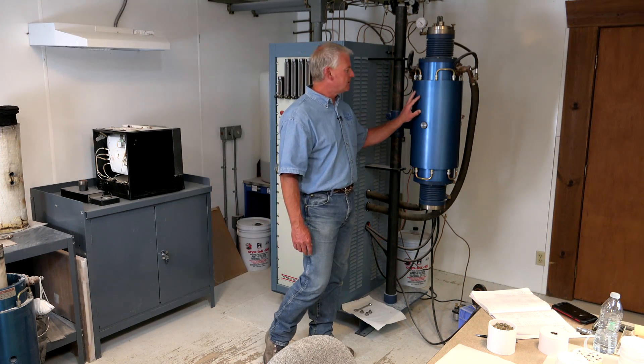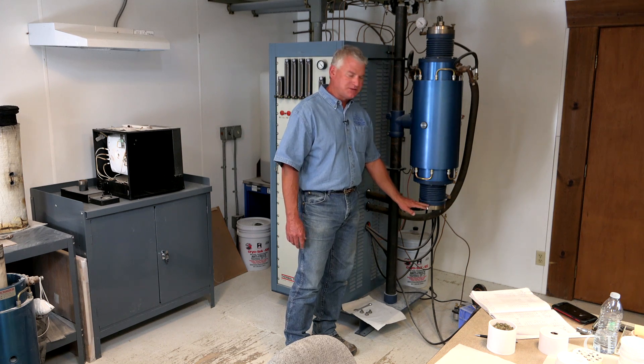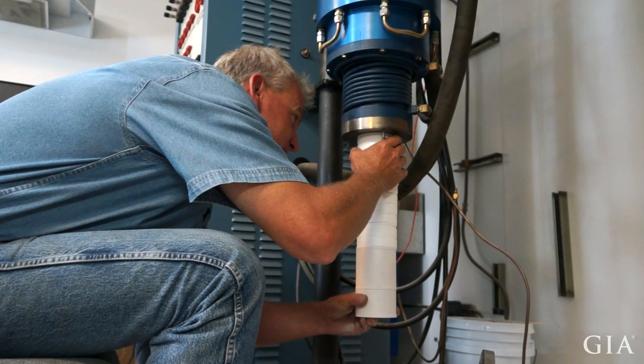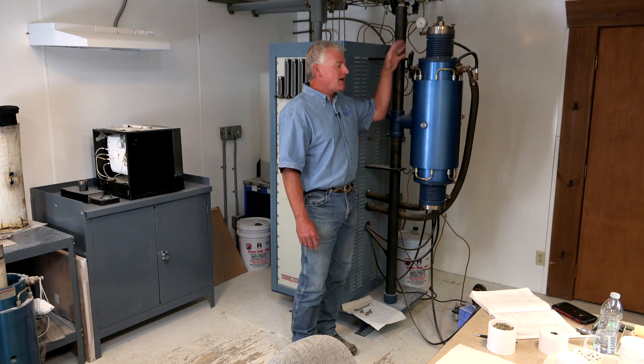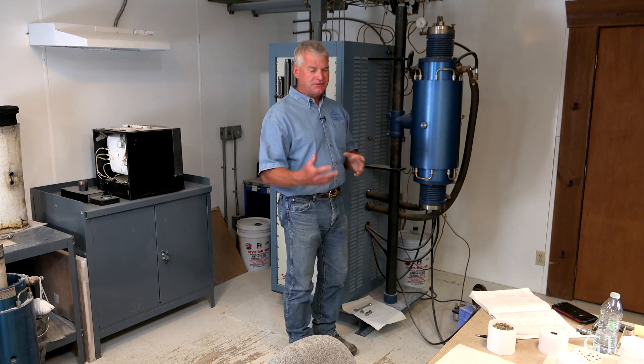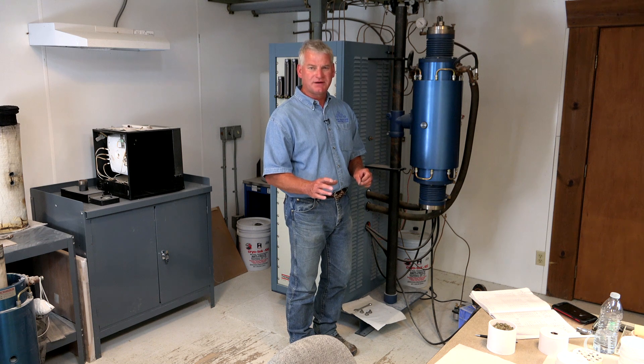This is the actual furnace body itself. The furnace can reach temperatures high enough that it could physically melt if not cooled. Inside the furnace body is an aluminum oxide tube approximately three feet long. The tube sits within the center of the furnace between nickel rings at the top and bottom — that is where the crucibles will be loaded. Because it's aluminum oxide, it's impervious, and we can add process gas. In the case of the fancy burn, it's oxygen; in the case of our blue burn, it's a combination of CO2 and hydrogen. If you're familiar with ceramics and glazing, you know you can influence the final color through either the oxidation or reduction of a mineral — and that, in layman's terms, is what we're doing within the sapphire as we heat treat.